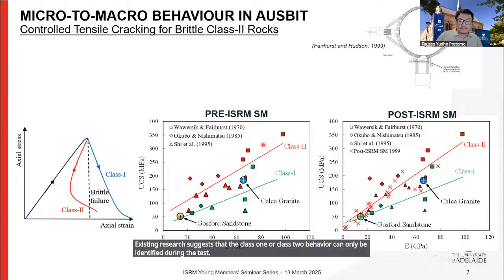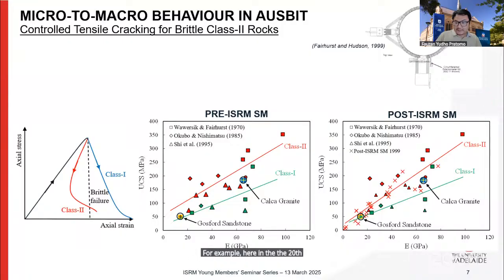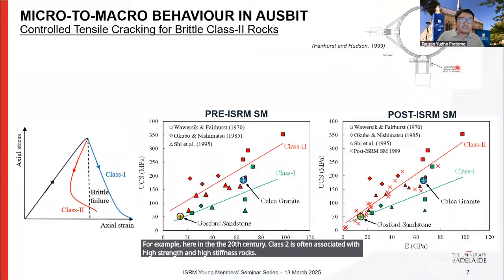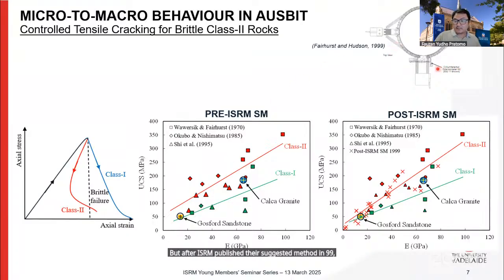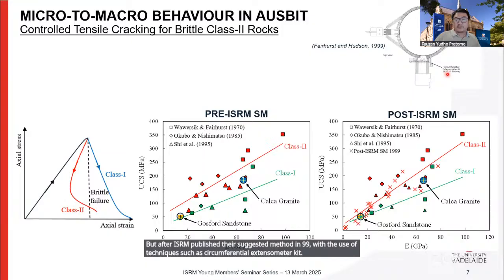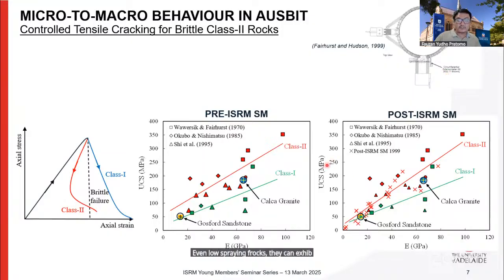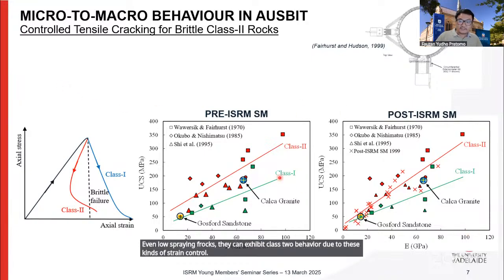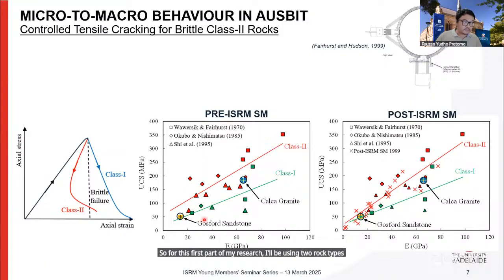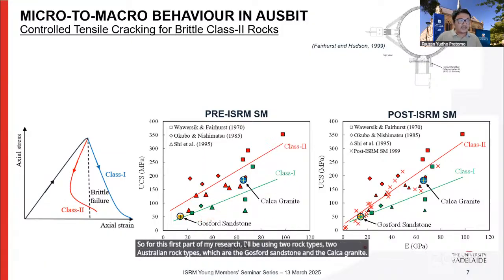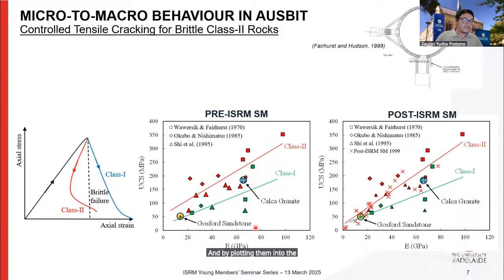For example, here in the 20th century, class 2 is often associated with high strength and high stiffness rocks. But after ISRM published the suggested method in 1999, with the use of techniques such as the circumferential extensometer kit, even low strength rocks can exhibit class 2 behavior due to these kinds of strain control. So for this first part of my research, I'll be using two Australian rock types, the Gosford sandstone and the Calca Granite. And by plotting them into the UCS and Young's modulus plots, they somehow show potential class 2 behavior.